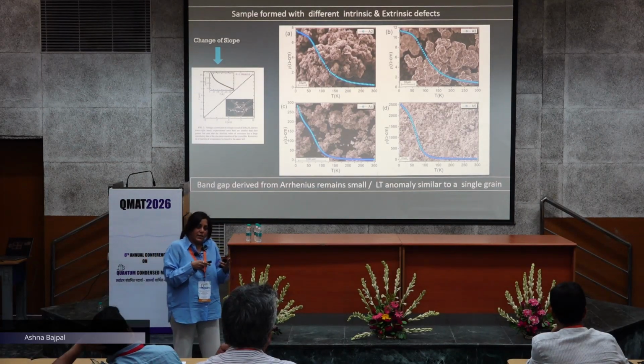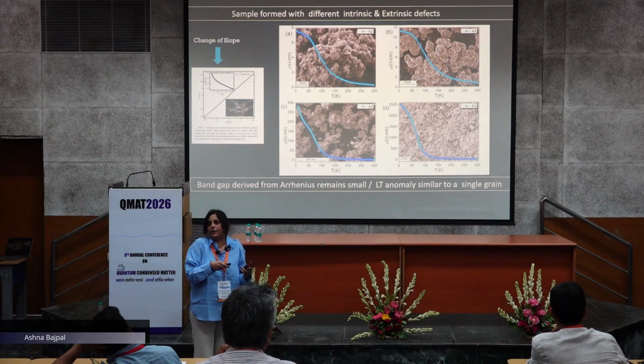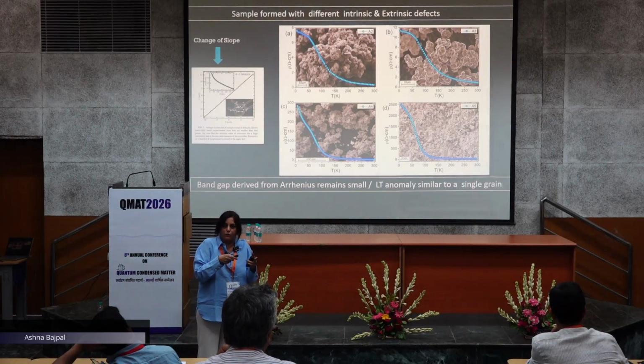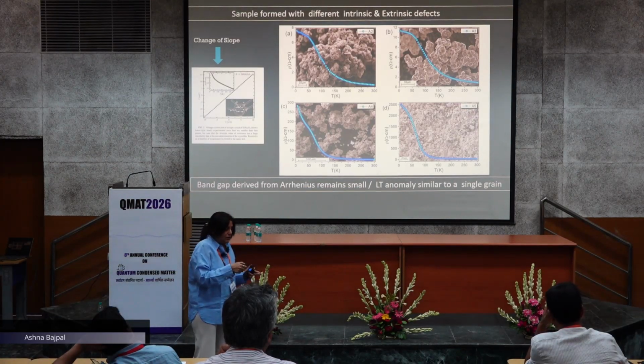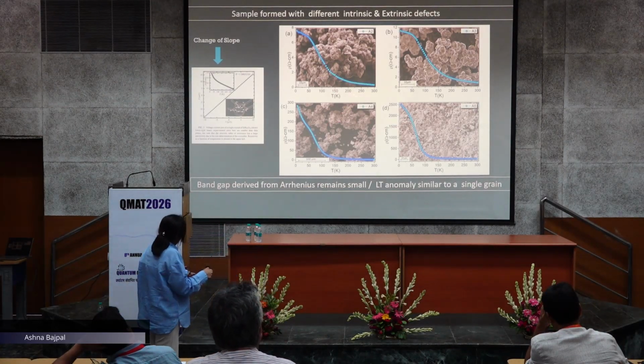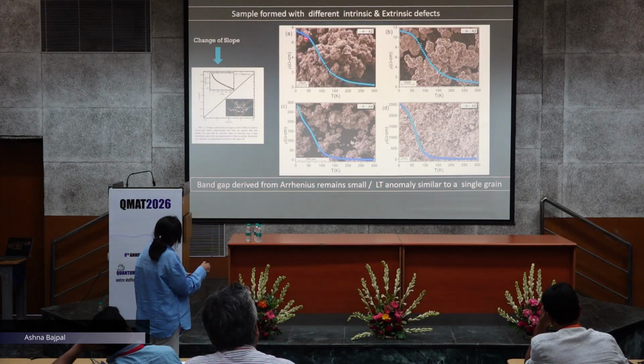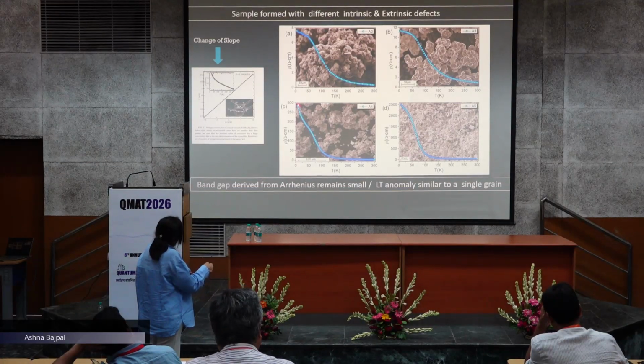So even though this system is very interesting magnetically, one has to understand why conductivity is in this fashion. So we found that Ru disorder plays a very prominent role. Below 50 K, of course, there have to be many iterations. There are variations and change of slope and all.